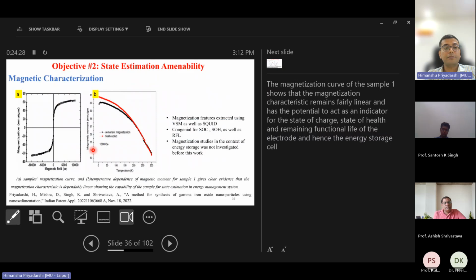If we see, I mentioned during the research gap identification that magnetic characterization was one important gap which we have addressed. Why? Because we have done magnetization using VSM, that is vibrating sample magnetometer, as well as SQUID, superconducting quantum interference device. So why have we done both? The natural question which comes is this: why? Because SQUID is used for lower temperatures, as we can see, and here the magnetization varies from 53 to 61. Generally for the bulk it is comparatively much lesser. And here also the MH curve we are seeing is quite linear. We will zoom into it in the later images and see how it is quite linear.